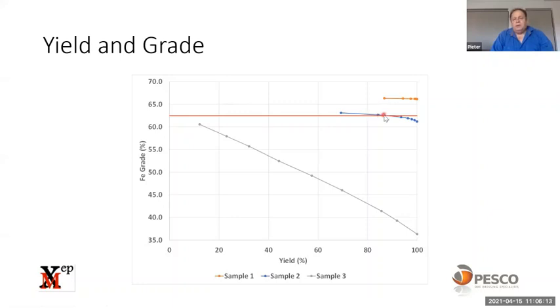The second line is a blue line that was tested at different densities and showed that the sample did achieve grade at about 85% yield. It made 62% Fe. The bottom line is a sample that's been tested and did not make grade. It did not achieve the required specified product grade. Therefore, maybe additional characterization tests will be needed to determine if the top size, the liberation size, can be reduced to improve the yield and the qualities.